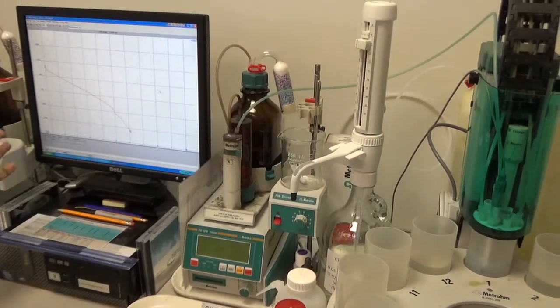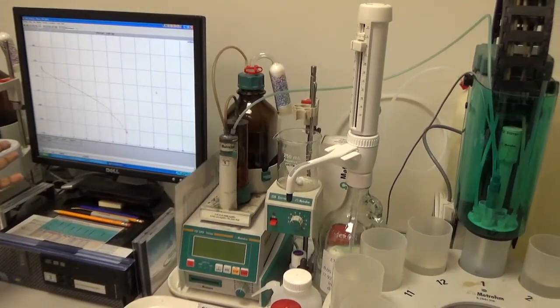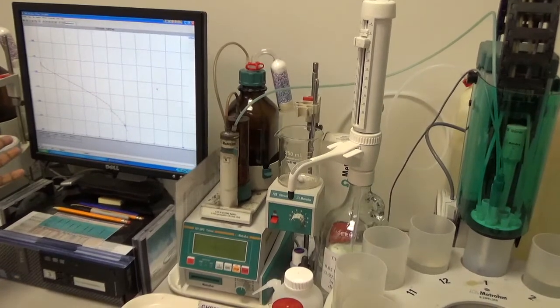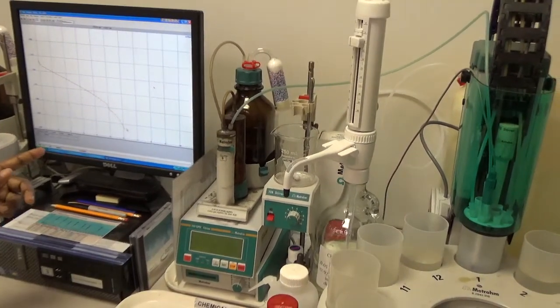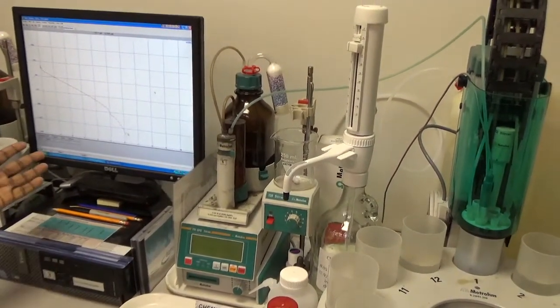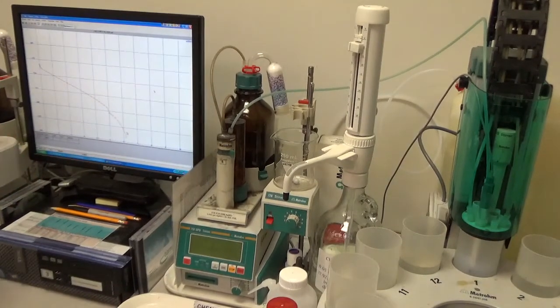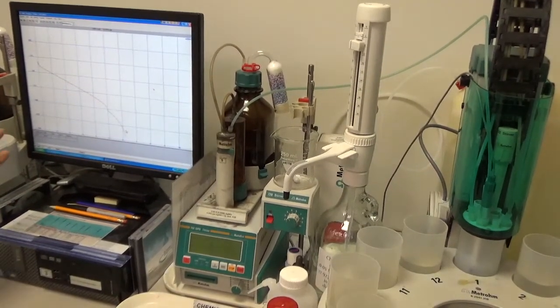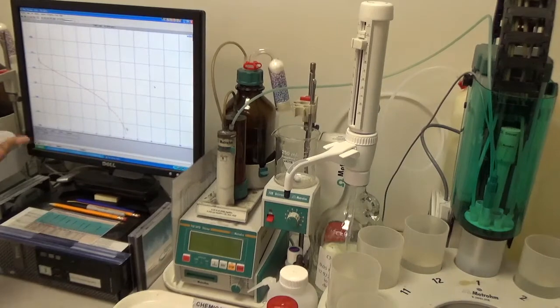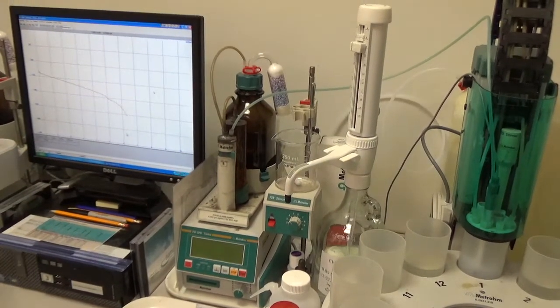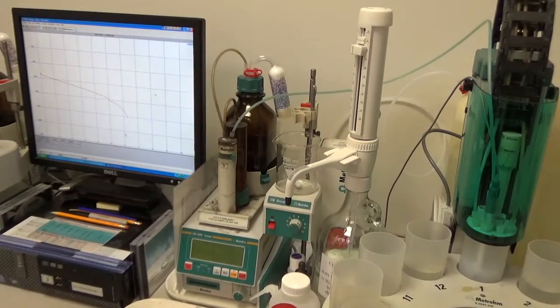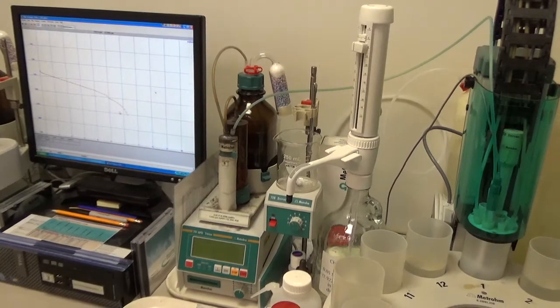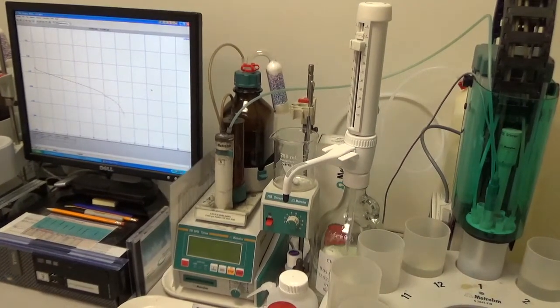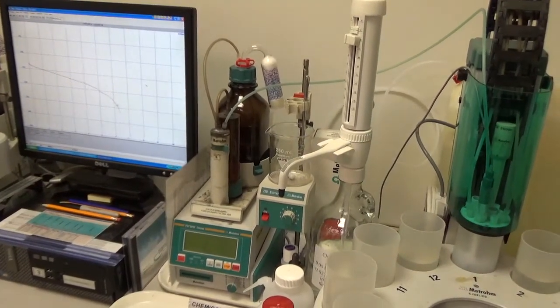There is a formula embedded in the macro to calculate the chloride content from the equivalence point, which is basically equivalence point times a factor 0.177 divided by the sample weight, which is 10 grams. For concrete samples, we take 10 grams of concrete. So equivalence point times the factor divided by the sample weight is the chloride content.